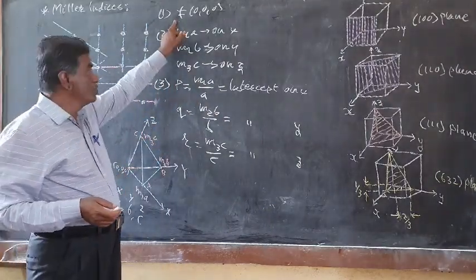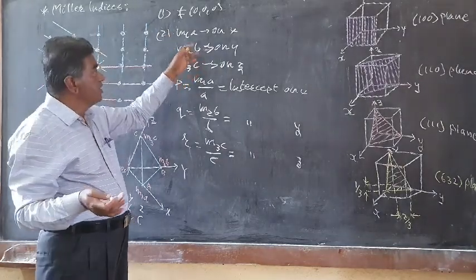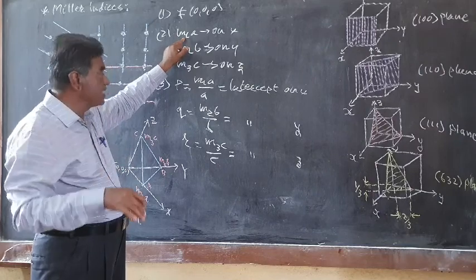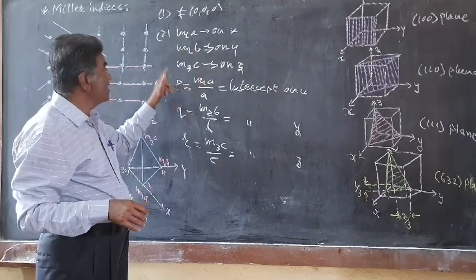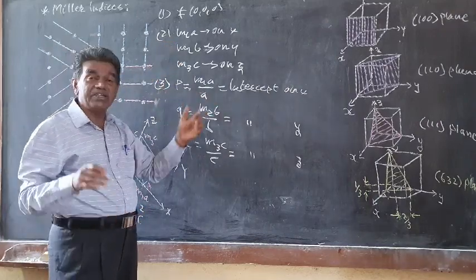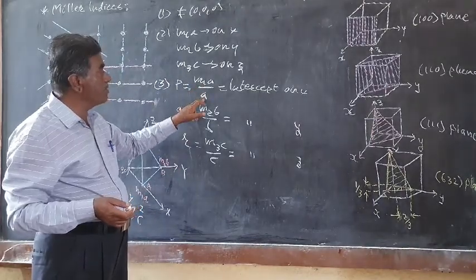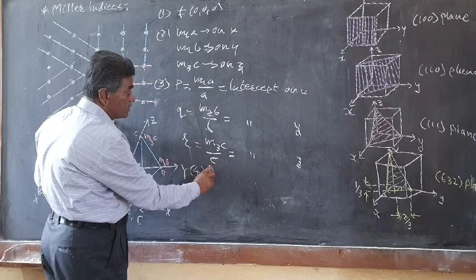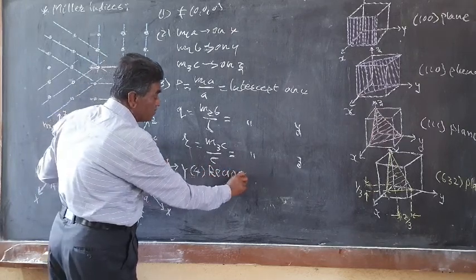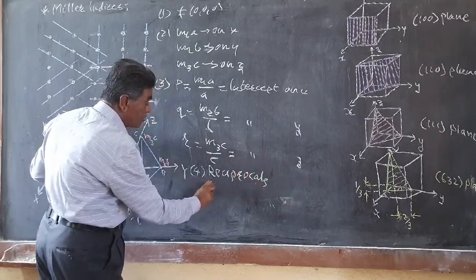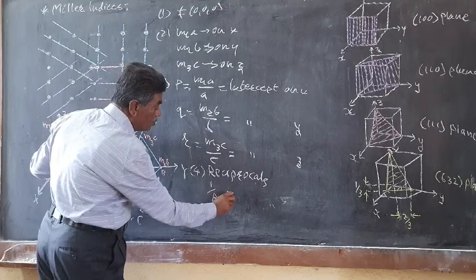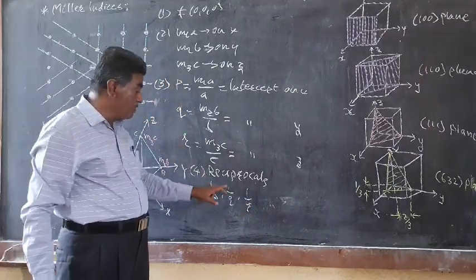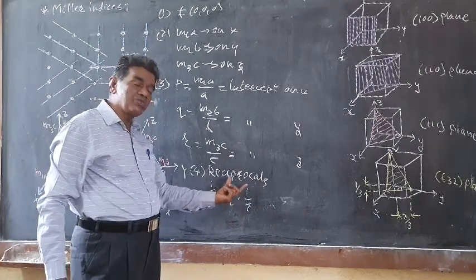To summarize so far: the plane should not pass through the origin; determine the coordinates of the intercept made by that plane on three axes; then convert those intercept coordinates in terms of unit cell parameters, giving p, q, r as the intercepts on x, y, and z respectively. The fourth step is to take the reciprocals of these intercepts: 1/p, 1/q, and 1/r.